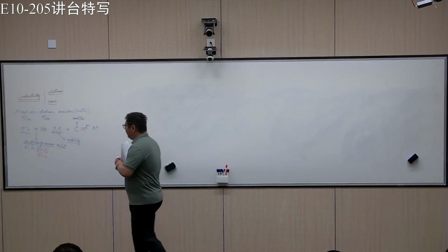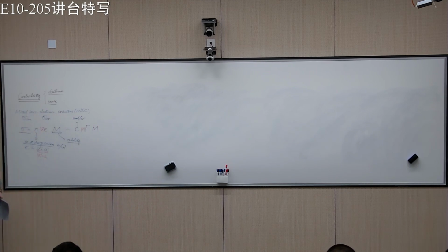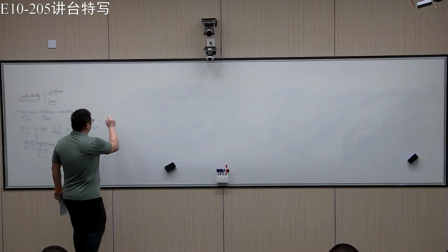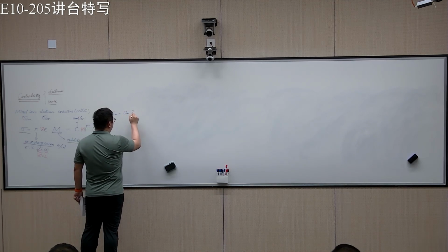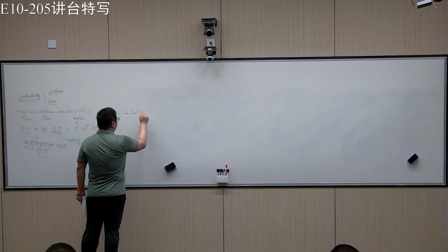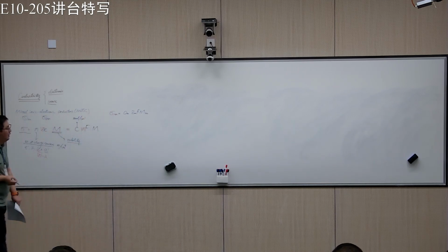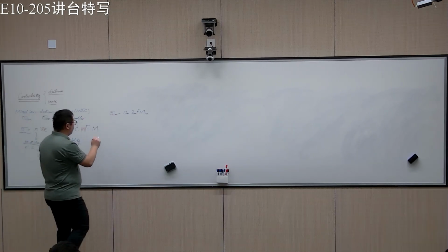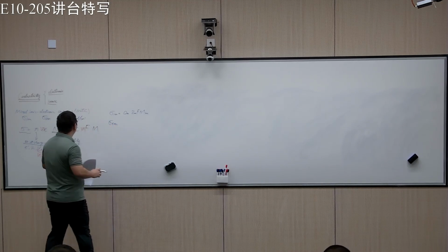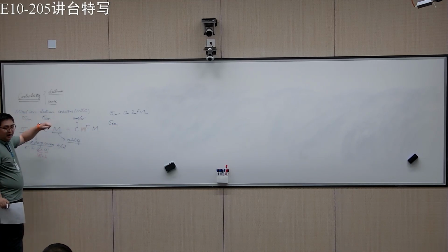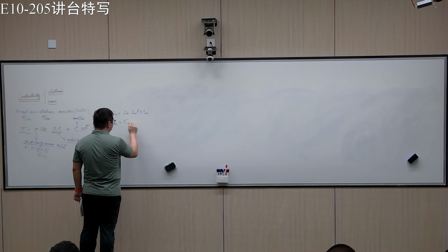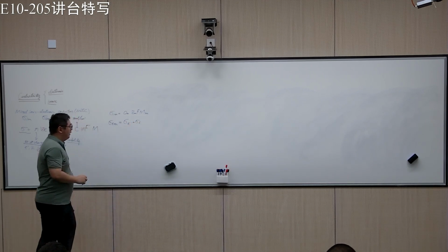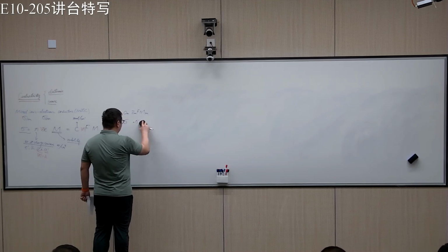So this equation is usually what we want. For example, the ionic conductivity should be Z times C_ion times F times mu_ion. This is the ionic conductivity. For the electronic conductivity of semiconductors, because most of these mixed conductors are semiconductors, you have to consider both electrons and holes, or what people usually write as n-type and p-type.